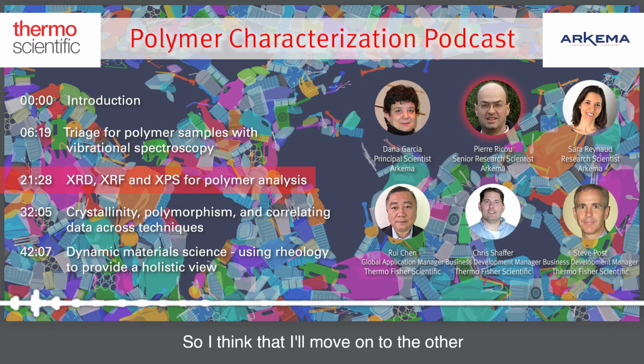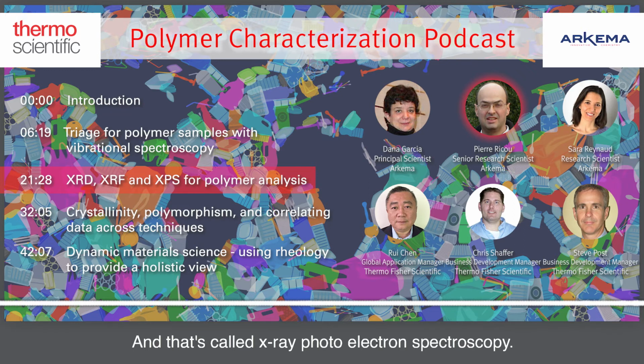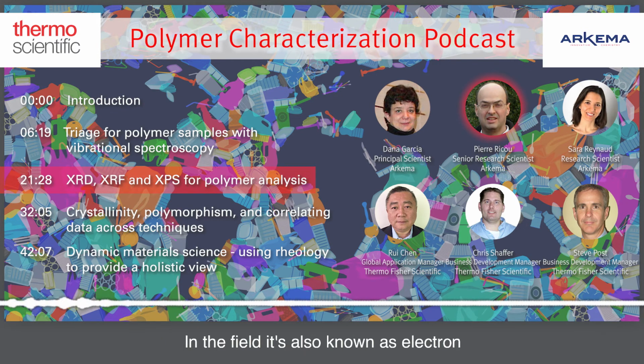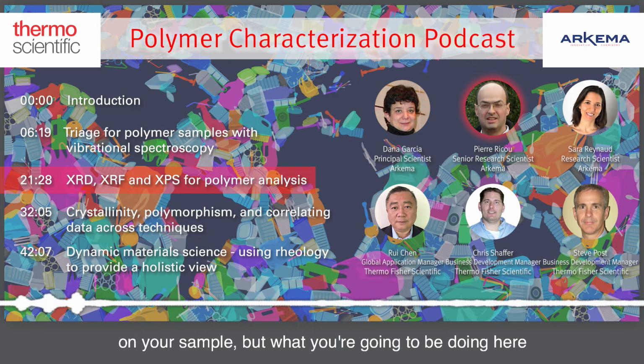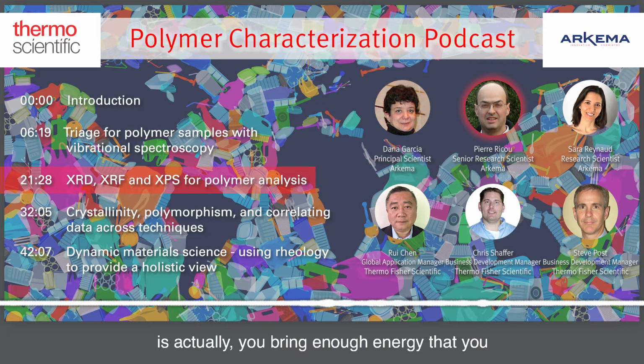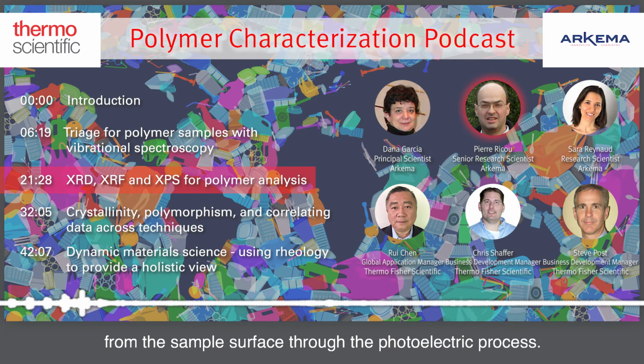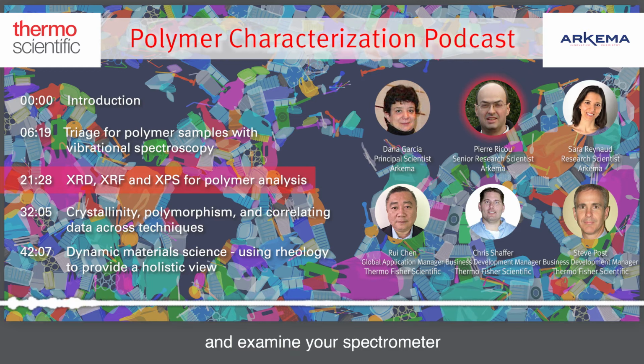So I think I'll move on to the other technique that we have in our laboratory that I'm in charge of, and that's called X-ray photoelectron spectroscopy. In the field, it's also known as electron spectroscopy for chemical analysis. So the same technique bears two names, and it's a very surface-sensitive technique. Once again, with that technique, you start with X-rays. You're shining them on your sample. But what you're going to be doing here is bringing enough energy that you are extracting electrons from the material, from the sample surface, through the photoelectric process. So you're extracting those electrons, sending them into your spectrometer, and what is of interest is to measure their kinetic energy, because you can relate that to their binding energy. So now, by measuring that energy, you can get some information.